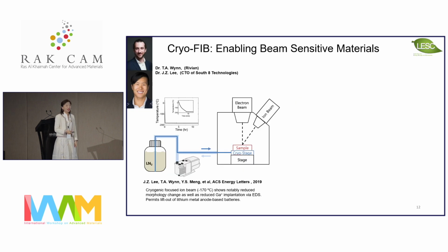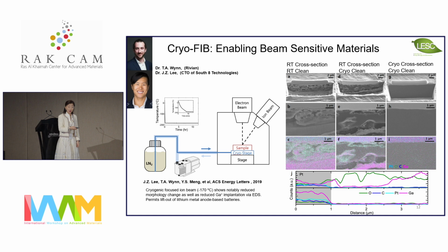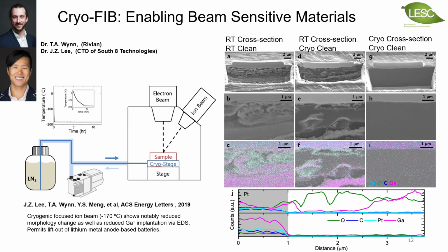Okay, first of all, it is really not easy to look at lithium metal. Okay? So if you use a scanning electron microscope and you use the gallium ion beam to cut the lithium cross-section to observe the cross-section of electrochemically deposited lithium, gallium actually reacts with lithium at room temperature. So everything you see here in the first 2 columns is not the true morphology of lithium metal. They are the reaction product of lithium-gallium alloys. And a lot of the earlier measurements were not correct because of this interference from the characterization tool.